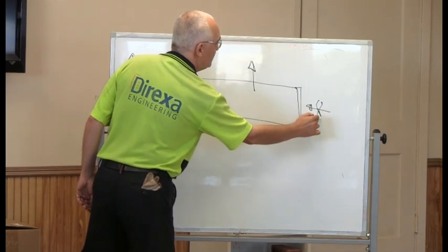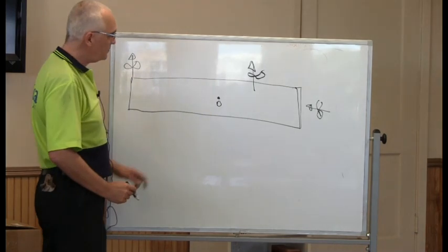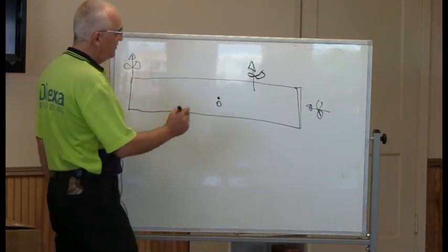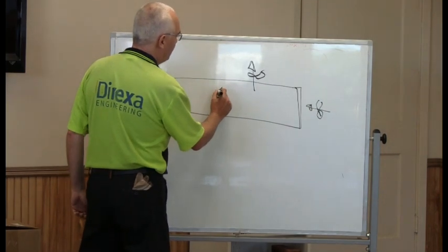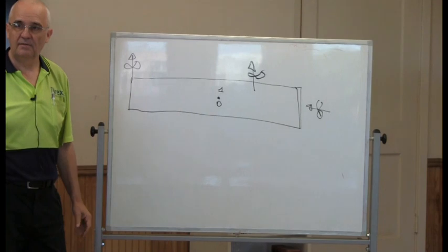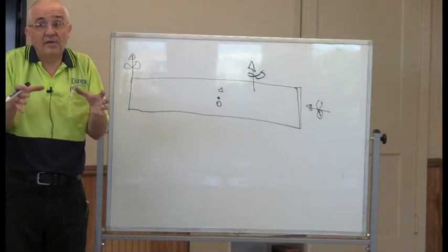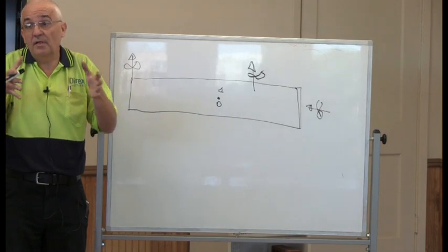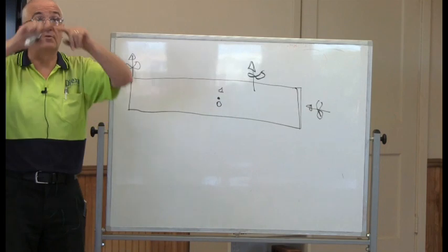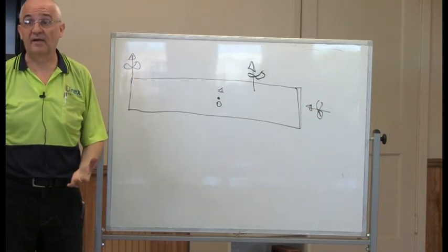overpressure and wasted recovery fan. To achieve that zero pressure, let's say that I need a pound of air. One pound of air. Okay? Because in that cross section, when I have 1 pound of air there, I create zero pressure in that area because I have a certain volume to occupy with a certain quantity of air. Right?